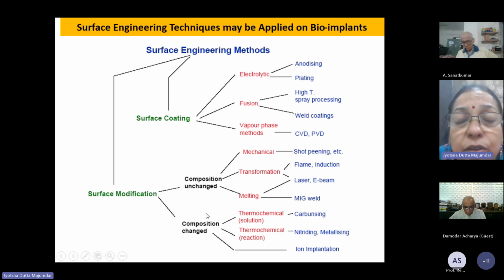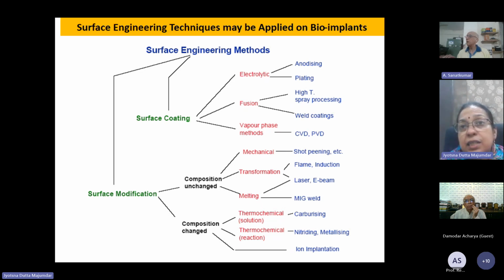Now, if you talk about surface structuring, if you talk about osseointegration, osseointegration can be achieved in two ways. Number one is by development of a bioactive coating, and number two is by roughening of the surface. Another approach followed prior to implantation of the metallic implant is sand blasting. They do sand blasting, shot peening prior to application of the implant in the human body. When sandblasting is done, it causes a lot of rough sites, rough grooves on the implant surface. When grooves are there, cells get anchored on the surface, because for all bioinert implant materials, particularly titanium based material or AISI316 stainless steel, the mechanism of cell adherence is mechanical anchorage, not really any spontaneous action.